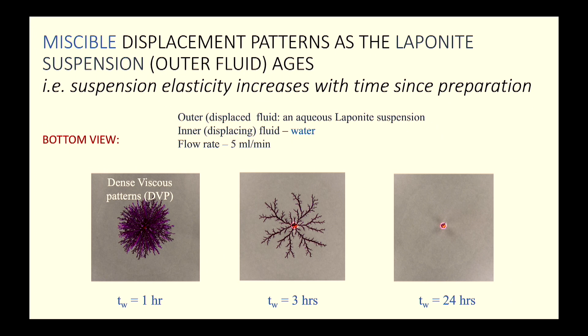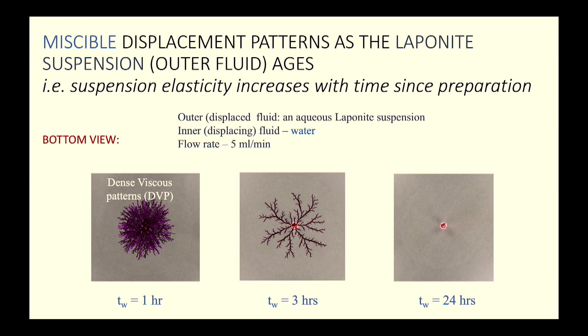When the clay is a little more elastic (aged three hours), the propagation becomes faster and beautiful patterns form — not tip splitting but side branching. Side branching occurs because the viscoelastic fluid competes: the fingertip tries to shear-thin the clay it is invading, while the driving pressure of water broadens the fingers, shedding side branches. These elastic effects become more and more prominent with age.